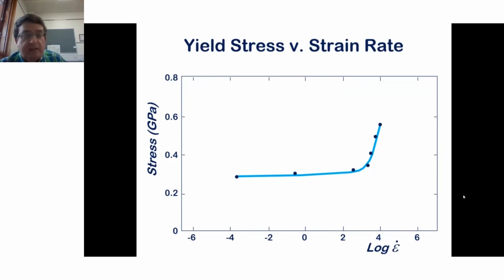The failure stress is kind of constant. It increases ever so slightly with strain rate, but it's not a huge dependence. However, when the strain rates got in the region of 10 to the 3, 10 to the 4, there was a big increase in the failure stress of the material. There were two reasons for this.